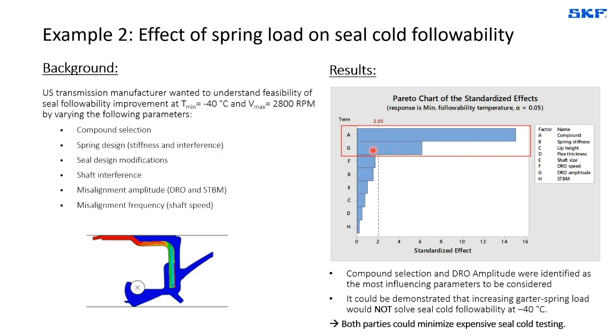Here we can see that the compound and the actual dynamic runout are the most important factors. And we could basically discuss with our customers and explain that increasing the load coming from the garter spring would simply not solve the problem at hand, since by increasing the garter spring load, we can simply not compete with the stiffness of the actual rubber at such a low temperature, since it is basically exponentially skyrocketing, and the rubber becomes even stiffer than the actual garter spring. So we could save both parties expensive seal cold testing and, of course, find different ways, thanks to our expertise, but also our SKF virtual seals, to respond to the customer need.